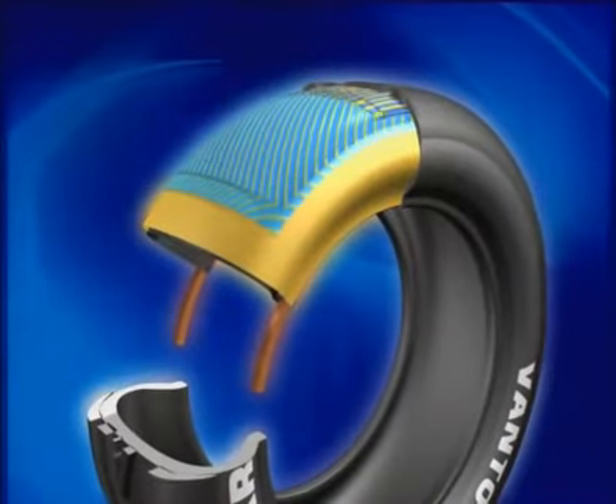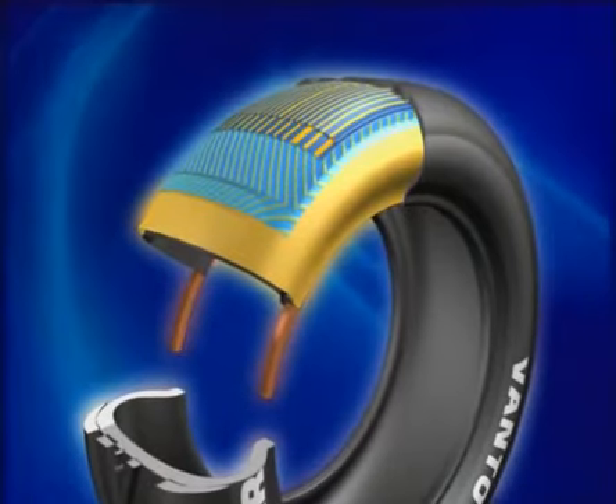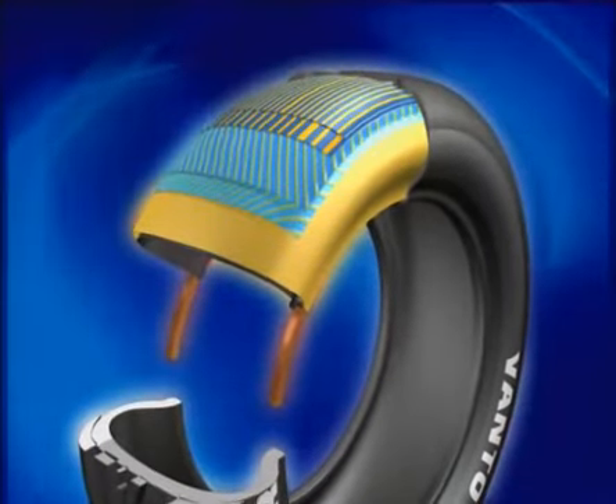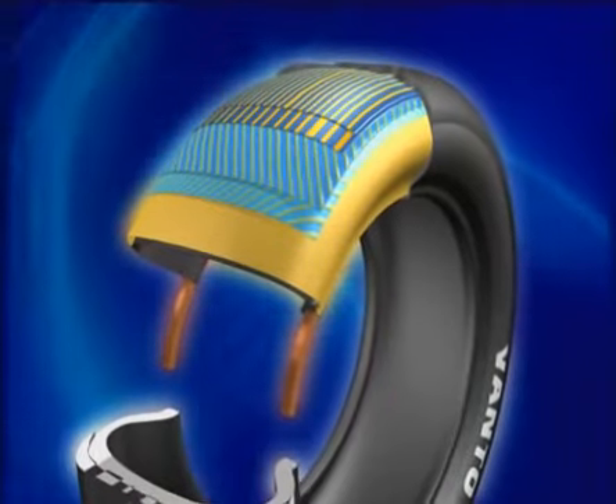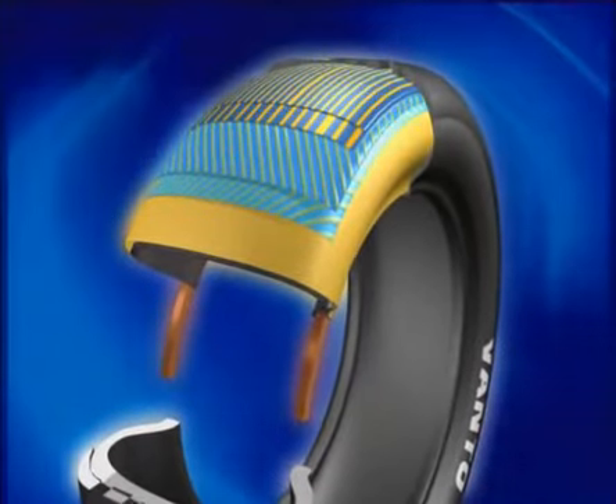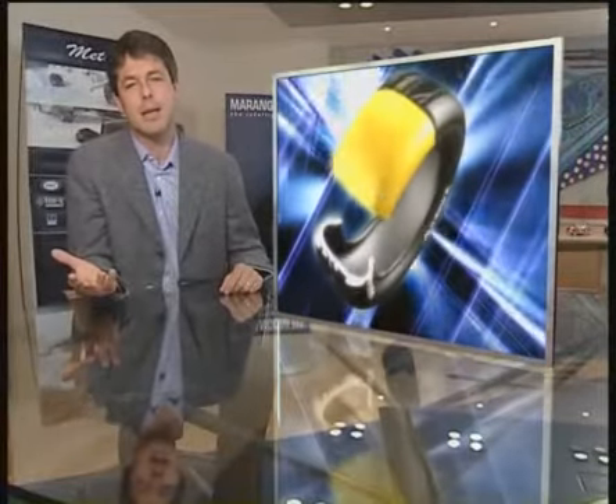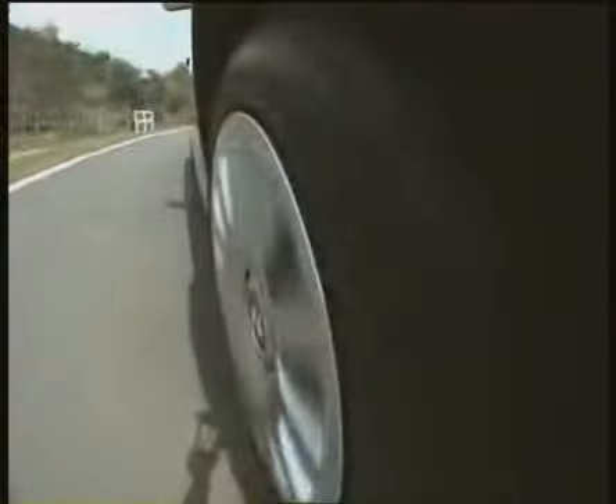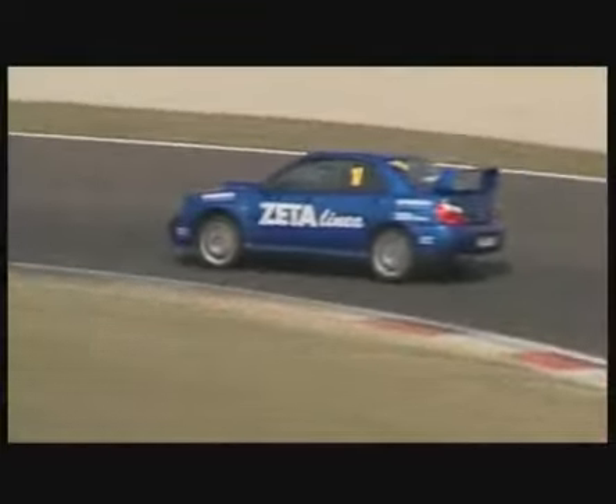Then there is the nylon spiral belt wrapped over the steel belts in one or two layers depending on the size of the tire, arranged at 0 degrees with respect to the tire rolling plane. The nylon belt is used in the larger tire sizes to improve resistance at high speeds, uniformity and ground contact area. Finally, there is the tread strip, that is the layer of compound in direct contact with the road surface. The tread strip is the element that transfers power thanks to its friction coefficient overcoming the so-called drift forces.